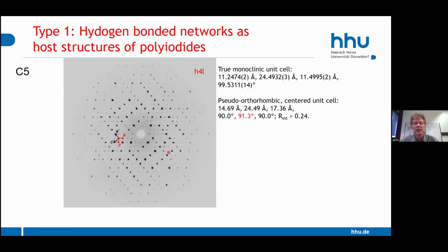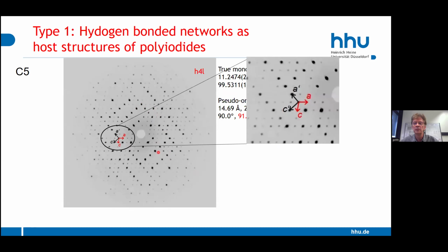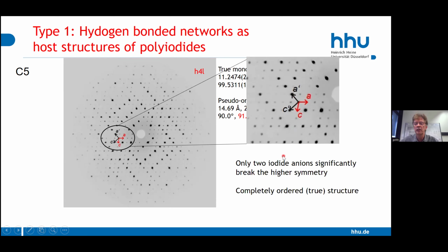So we have a diffraction pattern with really bright and dark spots. These are these intense spots in the diffraction pattern. And we have some smaller and not so intense spots between them. So we zoom it out and we can find out if we have this A/C coordinates, or this, then we are fixed only on the strong reflections, but the true unit cell is defined by these AC vectors, which then takes into account also these weak reflections.